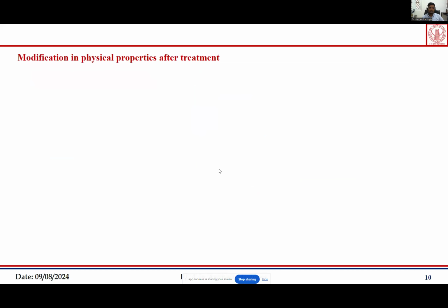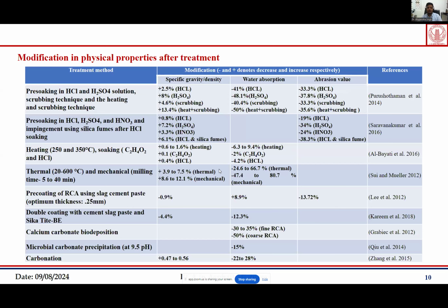Now moving towards the modification, people have used different modification techniques, and they have also combined different techniques, as we have discussed: physical, mechanical, thermal, and acid soaking techniques, and they have found that these techniques work really well. You can see the specific gravity has increased in most of the cases, water absorption has gone down, and abrasion value has also gone down. It ranges from acid soaking to pre-coating with slag cement, to calcium carbonate precipitation and MICP, and all those kinds of treatment methods people have utilized.